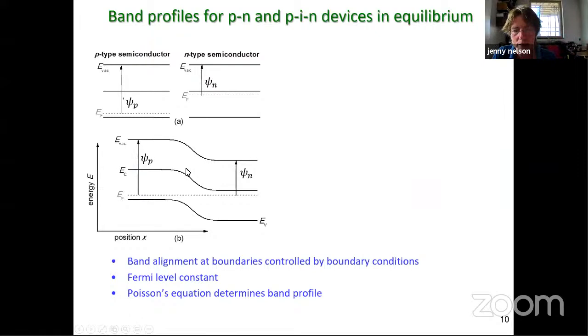So with this thing, we call it the PN junction. There is a direction that comes about because of the asymmetry. It's the same semiconductor, basically, on the left and the right-hand side of the junction, but one of them has got impurities that make it electron-rich, and the other one has impurities that make it electron-poor. And those small concentrations of impurities have a big effect on the energetics.